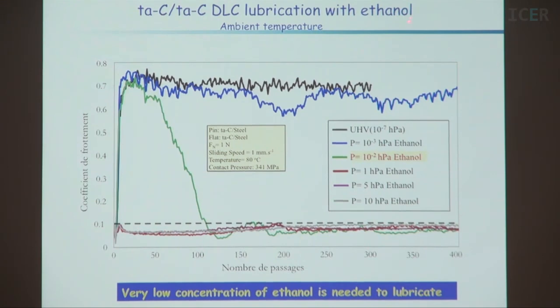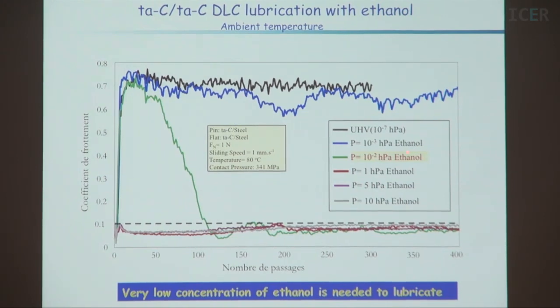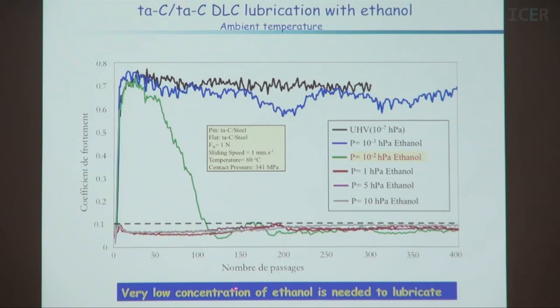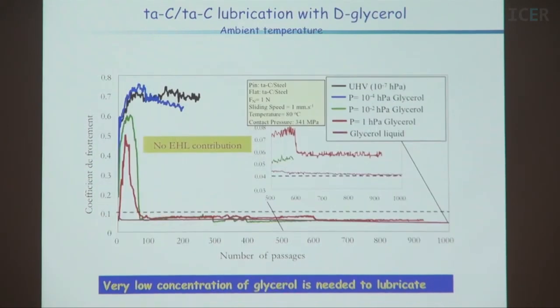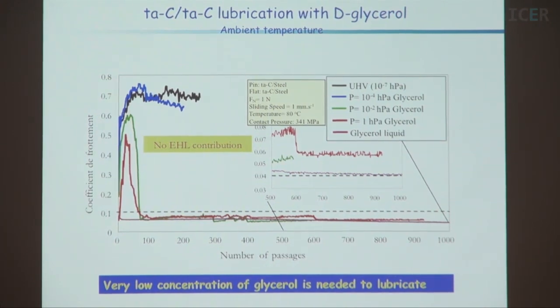We made also the experiment with ethanol. And again, we have the same story. 10^-2 hectopascal is sufficient to get the low friction. So a very low concentration of ethanol is needed to lubricate. This is another gas, glycerol, same story. In this kind of experiment, it is very interesting because you have no rheological effect, because the molecule is in the gaseous state. There is no liquid, no hydrodynamic lubrication.